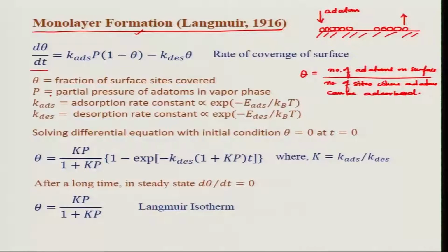This change in fractional coverage will depend on how much is the coverage first of all, and what is the rate of adsorption and desorption. K_ADS is the adsorption rate constant, which will depend on the adsorption energy, and K_DES is the desorption rate constant, which will depend on the energy of desorption, and also P, which is the partial pressure of adatoms in the vapor phase.